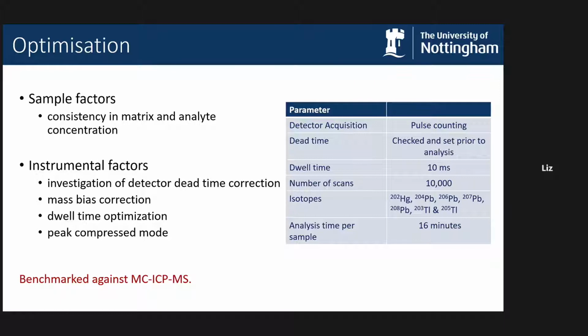We investigated the dwell time that the instrument should record at each isotope, the time it would sit at each isotope before moving on to the next one. Obviously, you want it to be long enough to maximize the counts, but not so long that the variation in the plasma as you move from one isotope to the next sequentially becomes too much of a problem.